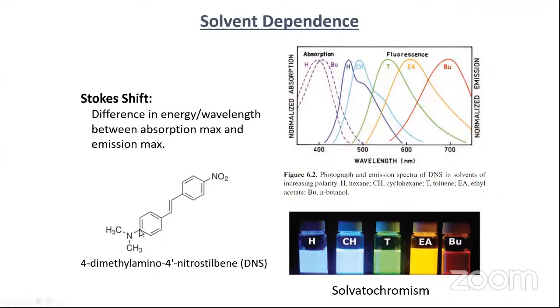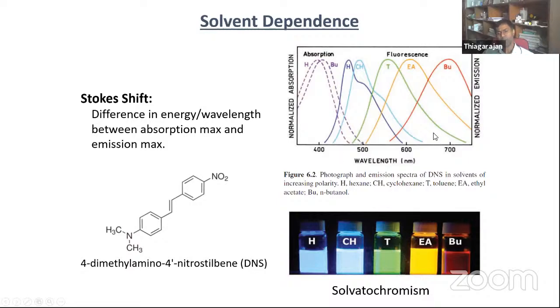You see it here. We have a donor, we have the acceptor, so the charge transfer occurs from the donor to the acceptor. When we use a more polar solvent, it stabilizes the charge transfer and the emission occurs at the higher wavelength. So you see in hexane it's in the blue, and in n-butanol you see it in the red. This way we can play with the solvents, tuning the polarity of the solvent, to tune the emission wavelength of the probe.